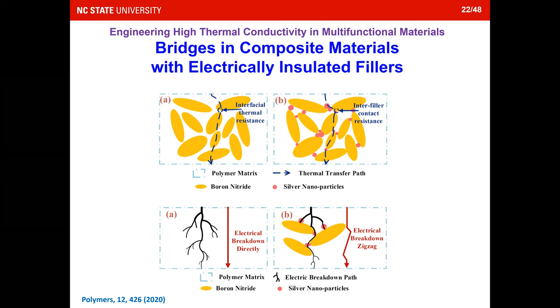If you don't have those fillers, the electrical breakdown is very easy and goes very directly across the film. But if you have those fillers, then the electrical breakdown has to go through a zigzag path. So that will be much more difficult for the material to break down. So we think that might be the reason for those combined properties. But we're not stopping here.